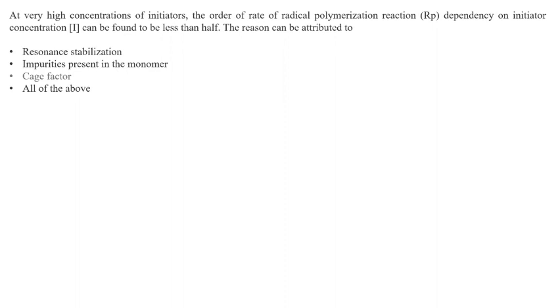In cage factor, radicals formed from decomposition of an initiator molecule are surrounded by a cage consisting of solvent or monomer molecules. So when the initiator decomposes and a radical is formed, that radical will be surrounded by the solvent molecules or the monomer molecules. When it is surrounded by this cage of molecules, within this cage, recombination of the radicals can take place and it will start deactivating the reaction. And since the initiator concentration is very high in the question, that is an effective factor. So cage factor is the factor which affects the rate of radical polymerization, Rp.